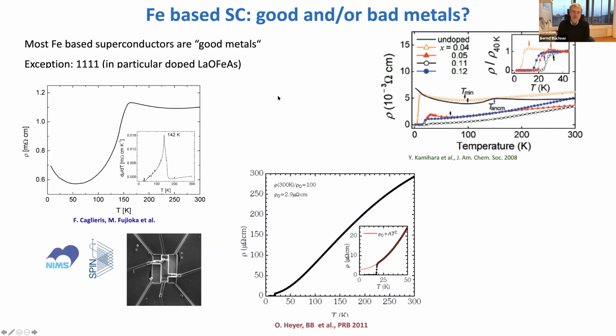And the smallest resistivity which I found so far was one which was measured in a small single crystal here, and you still see, if you look at the absolute values, this is far away from being a nice metal. And you see here these typical phase transitions. Above the phase transition, there's this increase, this tendency to localization. But the main message which you can take from such a figure is that there is a strong decrease of the resistivity when you do this ordering. And this immediately tells you that the scattering, which determines this very high value of the resistivity at high temperatures, is intrinsic. It's not extrinsic, or not only, mainly intrinsic. So you have a very strong intrinsic scattering, which is dominating the electronic transport, leading to the fact that these systems are very close to localization.